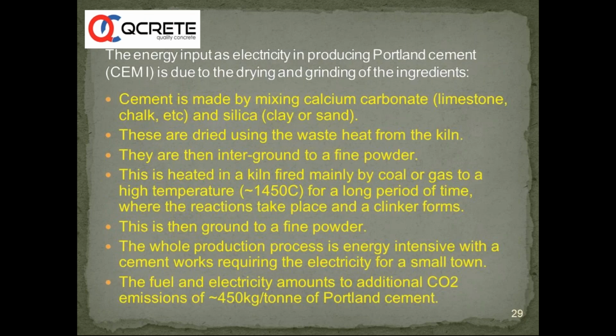Now, the most important point, other than these benefits, is the environmental benefits of fly ash in particular and SCMs in general, which has made usage of fly ash popular throughout the world. When we are manufacturing cement, it is made by mixing calcium carbonate and silica. These are dried using waste heat from the kiln, then ground into fine powder, heated up to about 1450 degrees, then ground into fine powder again. It is a very energy intensive process.